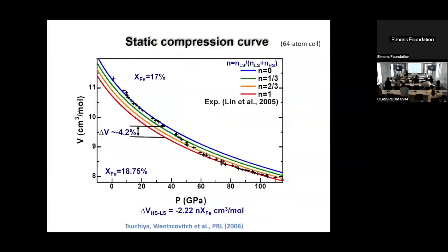This is huge. And this is what we started doing in 2004. The DFT plus U was not even published, as we know today, but that was in collaboration with co-author Stefano de Gironcoli. So here is, for example, 18.75% iron. It's 64 atoms per cell, and I have 6 iron ions. This is MgO, right? Six iron ions, and they are as far as possible from each other.